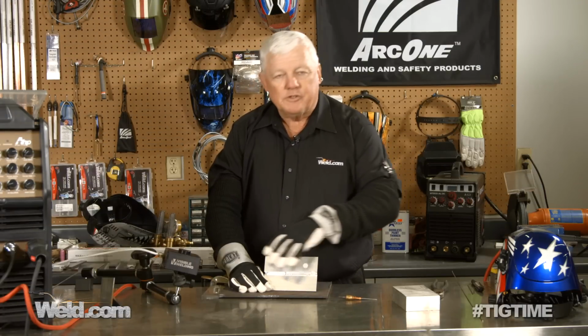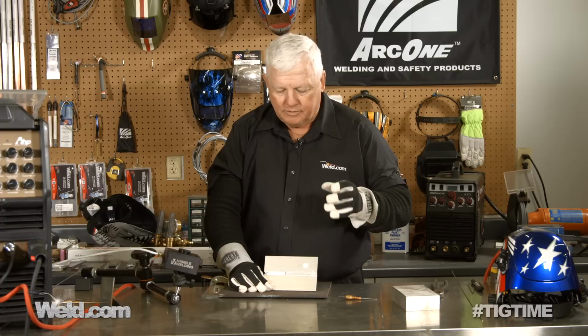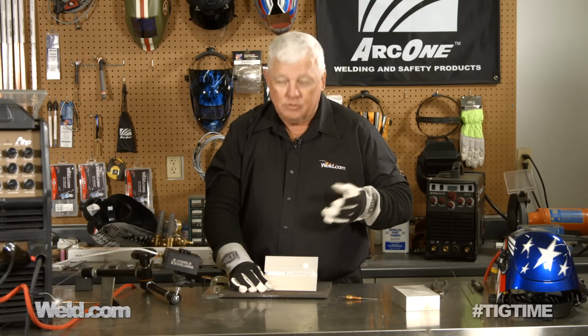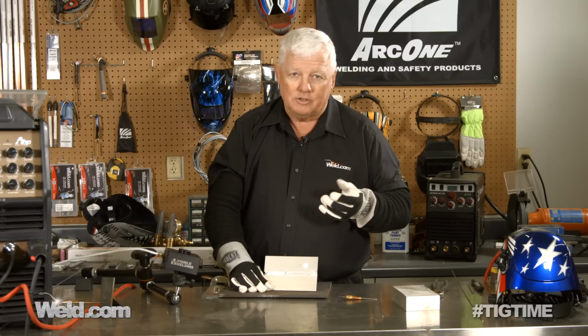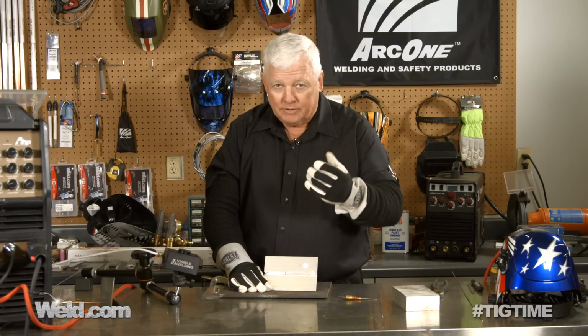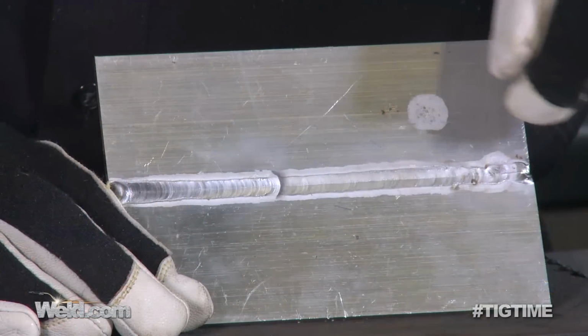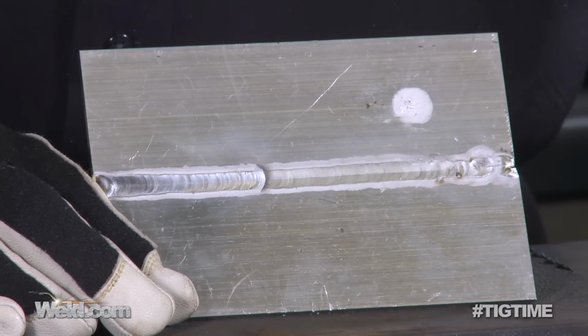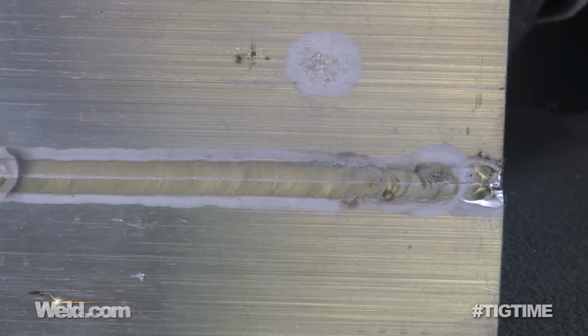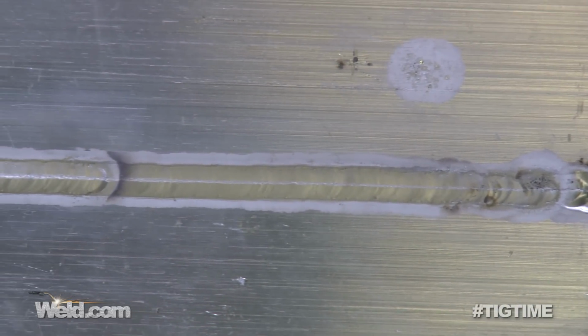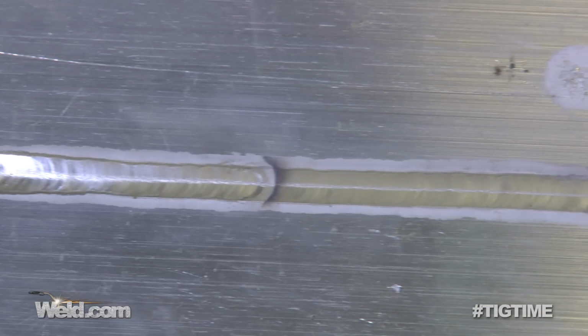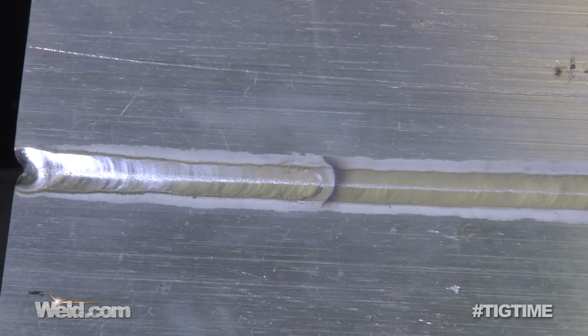Okay, now we've let this part cool off and really to show what hot short cracking will do to you. And I say to you because there's no advantage to hot short cracking. I don't know if you can get the cameras to zoom in far enough, but right down the center of the weld, it's starting to crack. And it's almost all the way across. The only thing holding it is probably less than a few pounds per square inch pressure.